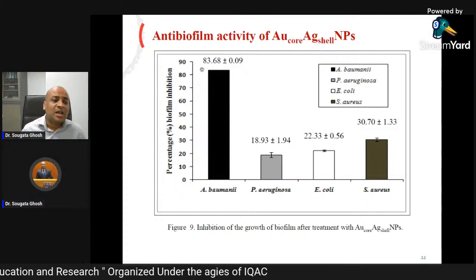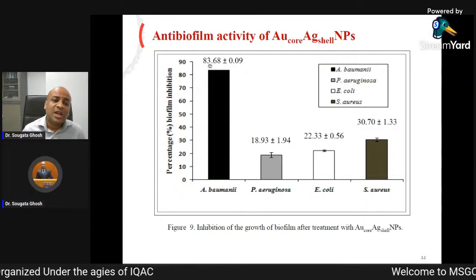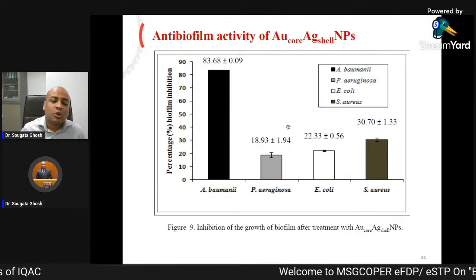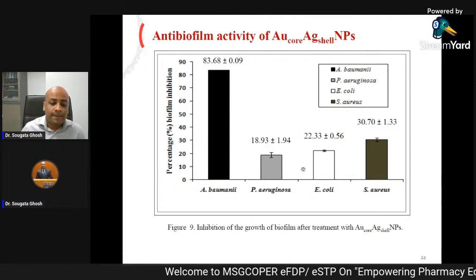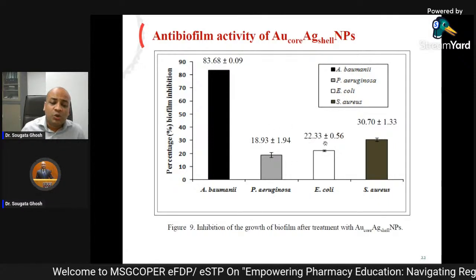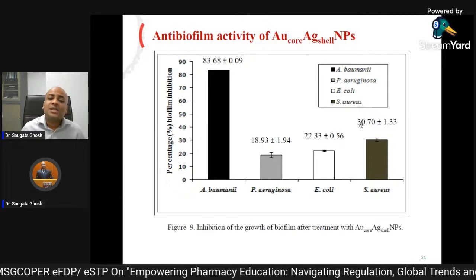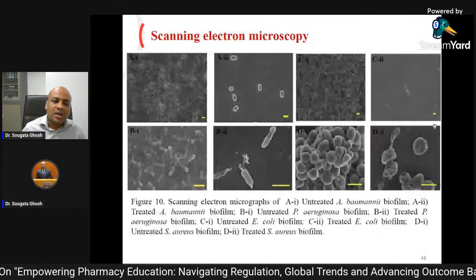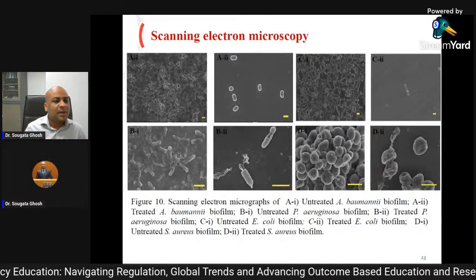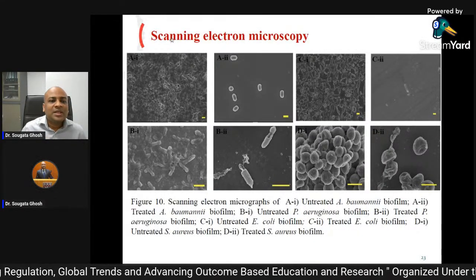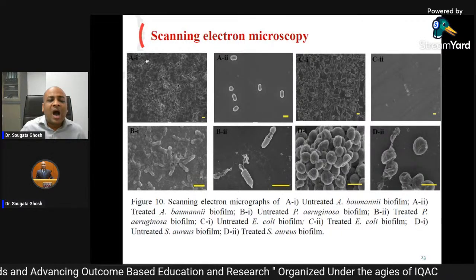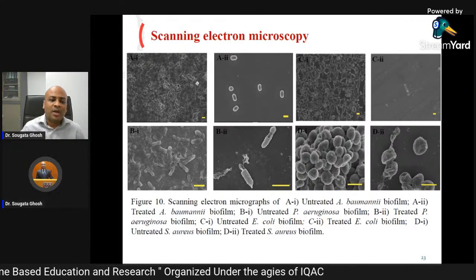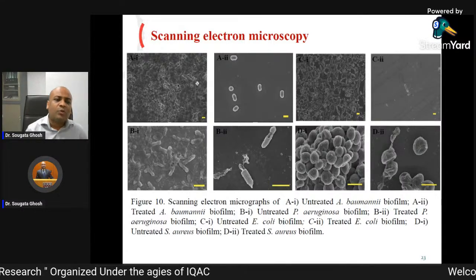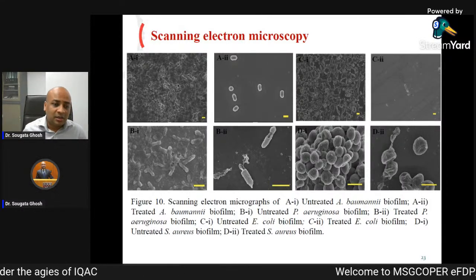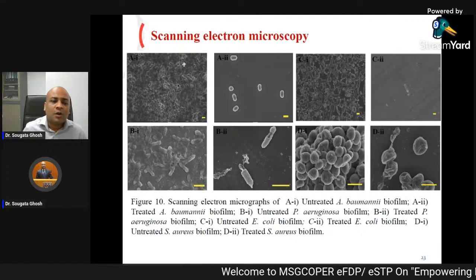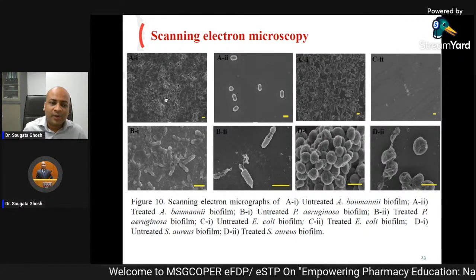So this nanoparticle could inhibit Acinetobacter baumannii more than 83%. It could inhibit Pseudomonas aeruginosa more than 18%, E. coli up to 22%, and Staphylococcus aureus 30%. So it was very important. Now we wanted to see what is happening inside the biofilm. Here you can see scanning electron microscopy of untreated biofilm of Acinetobacter baumannii. The biofilm was completely intact. You can see the whole surface was covered with Acinetobacter baumannii cells, biofilms.